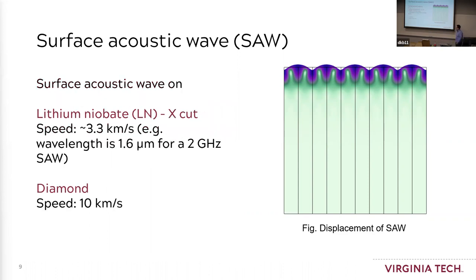And how fast are those surface acoustic waves? A typical number for lithium niobate, it depends on the crystal cut, is about 3.3 kilometers per second. What does it mean? It means for a 2 gigahertz microwave signal, very close to what we have for the original wideband, 2.5 gigahertz, it will have a wavelength of about 1.6 micron.